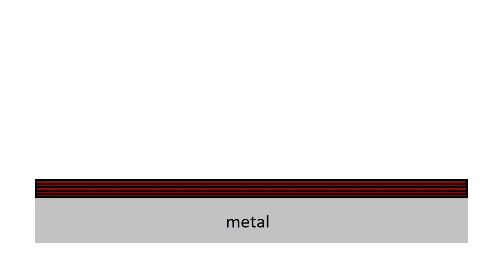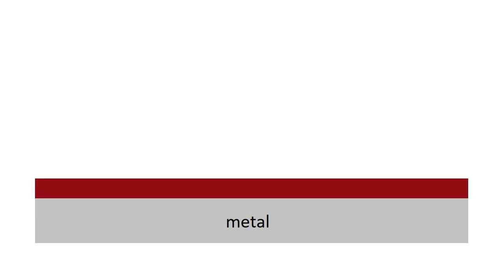However, this would take 10 hours to achieve, and the oven would be left on for 5 of those hours, which I felt was extremely wasteful. So I decided to do one thick layer instead of multiple thin layers. This was a big mistake.